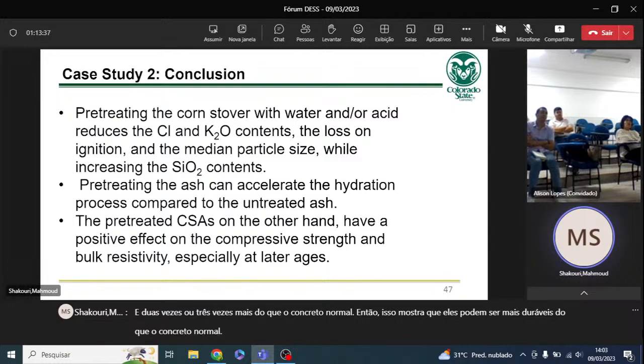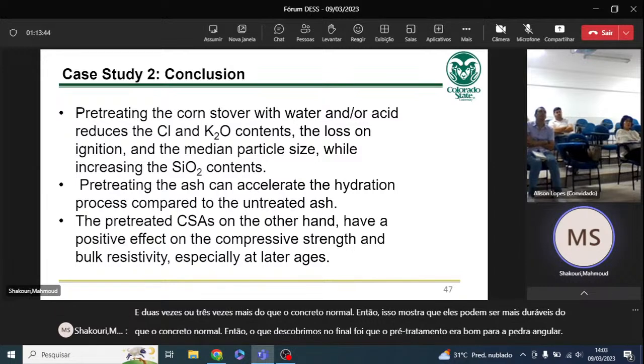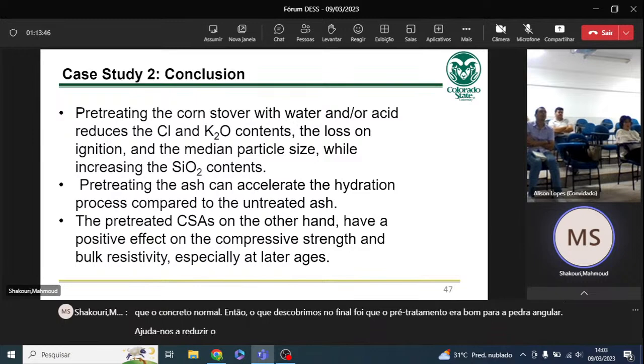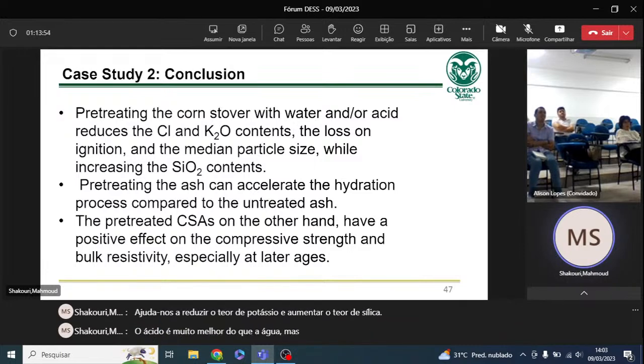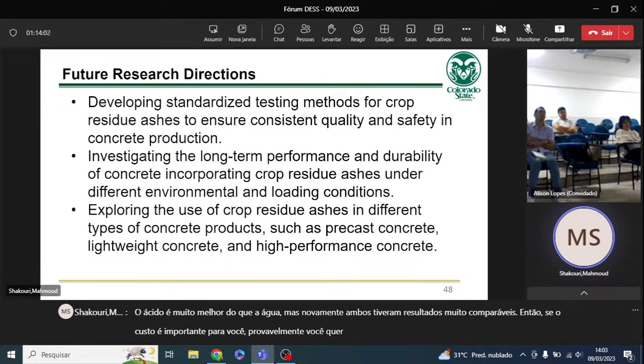So what we found in the end was that pre-treating was good for corn stover. It helps us reduce the potassium content and increase the silica content. Acid is much better than water, but both of them had comparable results. So if cost is important for you, you probably want to go with water.